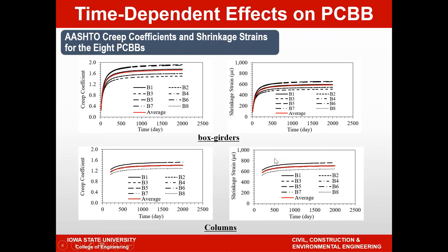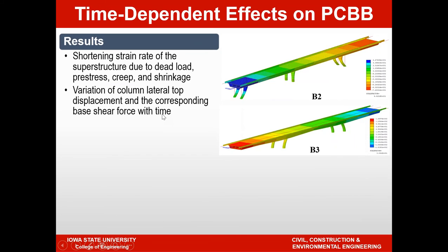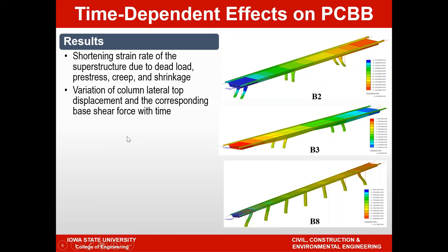Let me show you some results of the analysis. So shortening strain rate of the superstructure due to dead load, pre-stress, creep, and shrinkage were evaluated, and then we followed and figured out the column top lateral displacement, and recall that we have also activated the relaxation, so that relaxation is active in these analyses. What you're seeing here is two of the bridges, B2, B3, along with B8, which is the longest bridge that we analyzed. And you can see in these columns, especially B8, the extreme columns will undergo much larger deformation. The columns close to the center of the span may not experience any significant movement.